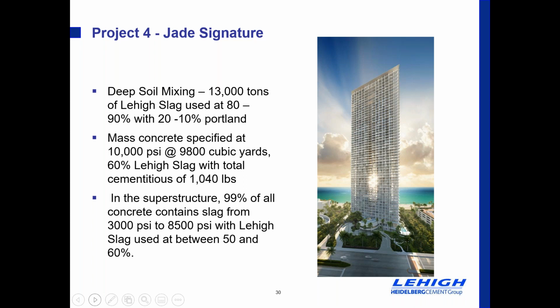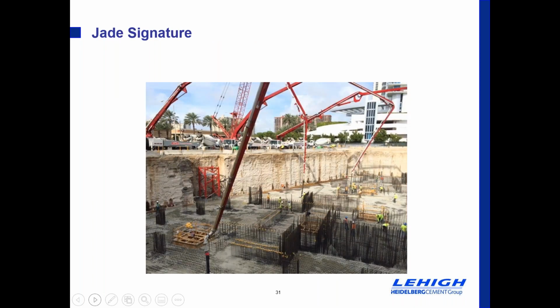And then of course, once the project is done, we move to the superstructure, and all of the material in that structure between 3,000 and 8,500 use slag at between 50 and 60%. Next slide.